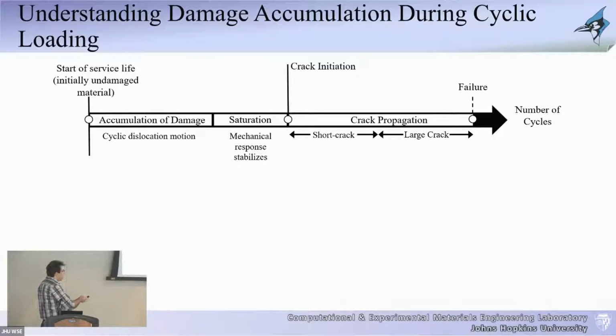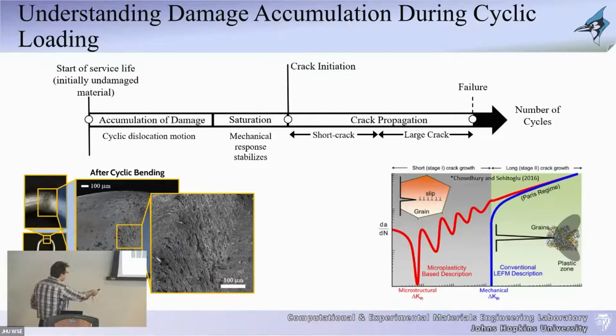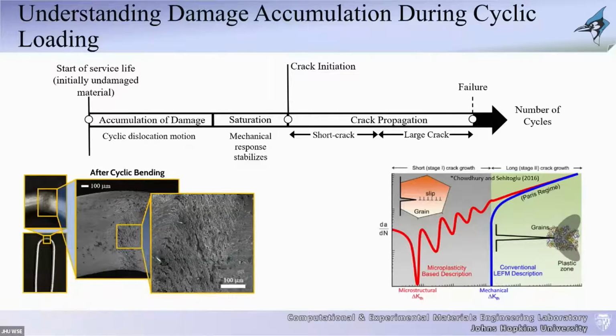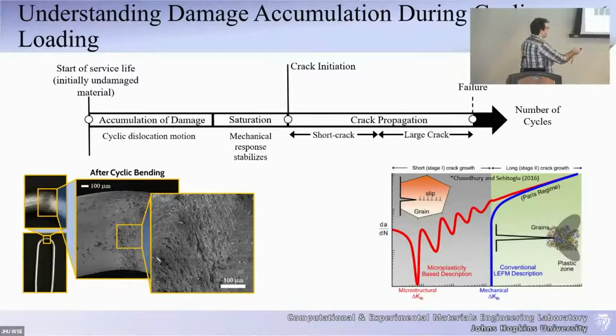And eventually there's typically a lot of these short cracks that form. If I forward quickly over here, notice there's a lot of these cracks with different sizes. A lot of them are short. Not all of them contribute to failure. Eventually, some of them will dominate, and that leads to large cracks, and then the large crack propagates until you get complete failure. Now, we understand in the mechanics world, in the materials world, quite well, and we can predict quite well this behavior, the large crack propagation and failure. So this can be classified using what is known as the Paris regime or Paris law.